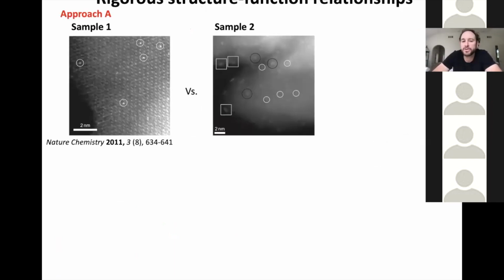So first question is, how do we develop rigorous structure-function relationships where we can convince ourselves that these atomically dispersed metals actually have the behavior we're assigning to them? One approach, and this is not meant in any way to put down this particular paper, this is just an example where something like this was done because I do think this was pioneering work. In one case, you can look at two samples. You can look at electron microscopy and say, we could only see single atoms here, and here we could see lots of clusters. So let's compare their reactivities, and this will give us some measure of the difference in their performance.